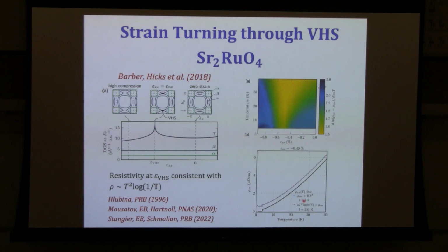It turns out there were later experiments by Cliff. You cannot actually extend this measurement below 3 or 4 Kelvin because the system goes superconducting at that point, so you cannot measure resistivity anymore. In fact, superconductivity is extremely strongly enhanced exactly when you tune the system to the vicinity of the Van Hove singularity. But Cliff has since done experiments where he suppressed superconductivity by applying a magnetic field, and he claims that the T squared log T actually fits the data better when you go to lower temperature.